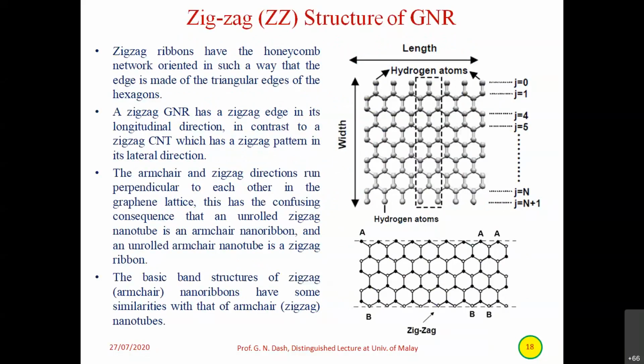So, zigzag structures. Zigzag ribbons have the honeycomb network oriented in such a way that the edge is made up of triangular edges of the hexagon, as you can see. And zigzag GNR has a zigzag edge in the longitudinal direction, in contrast to the zigzag CNT, which has a zigzag pattern in the lateral direction. The armchair and zigzag directions run perpendicular to each other in the graphene lattice. This has the confusing consequence that an unrolled zigzag nanotube is an armchair nanoribbon and an unrolled armchair nanotube is a zigzag ribbon. And one very important difference is that in zigzag, all the A-type atoms are on one edge and all the B-type atoms are on the other edge, whereas in armchair, we have seen that they are AB at both the edges.